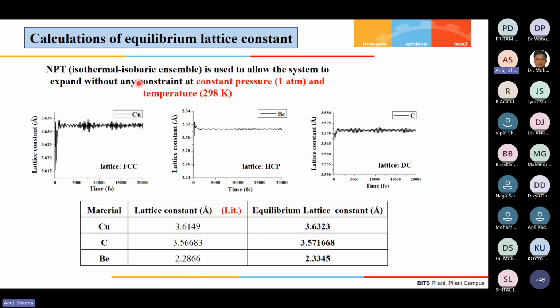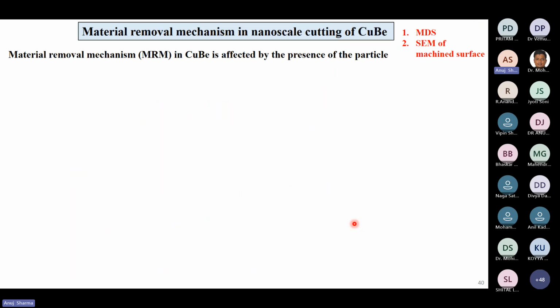So for that, the NPT dynamics were run, and it was seen that there was an initial fluctuation, and after that they were just fluctuating around some constant values, for all the lattice parameters for copper, beryllium, and carbon. In this region they were averaged out, and it was found that there were some differences from the lattice constants in the literature. So these lattice constants were considered for creating the structure in the MD simulation code. And once the structure was defined in the MD code, the MD simulations were carried out, and results are being presented here.